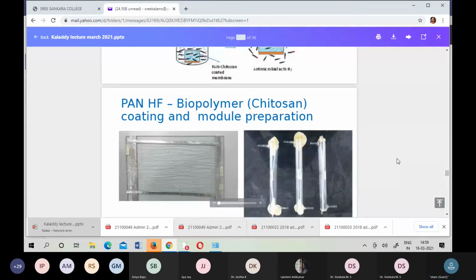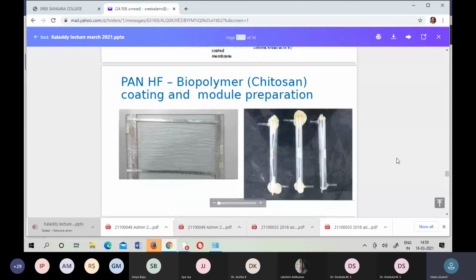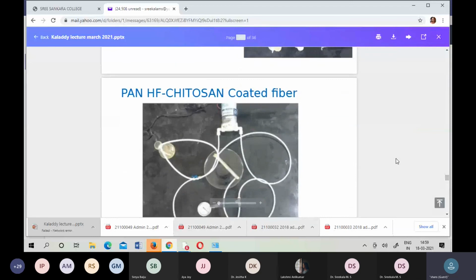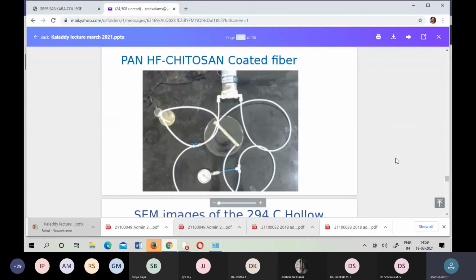biological fouling. So we have the PAN membrane we casted, whatever the casted hollow fiber, and we use a concentration of close to 1 to 2 percent of chitosan, which we dissolve in acetic acid, and we have the solution. And we also did the cross-linking. This is a schematic figure showing how the cross-linking is happening. These materials resist microbes, and we get a PAN membrane coated with chitosan, a hollow fiber membrane with fouling stability. So this is how we did the coating.